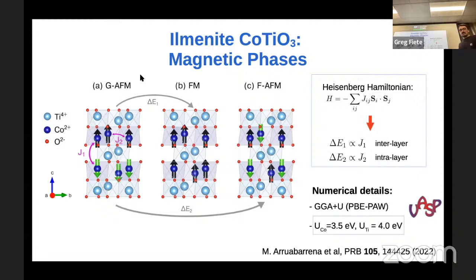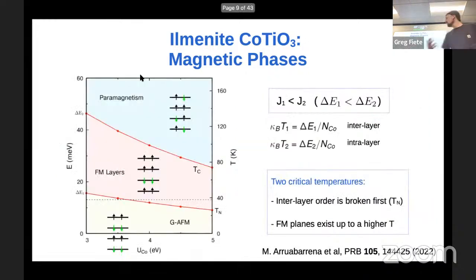What we found when studying the magnetism of this compound via the J1 and J2 constants was the following. We were able to make a phase transition diagram in which we observed that the ground state was effectively the experimentally observed GAFM state, with ferromagnetic cobalt planes that are antiferromagnetically coupled in the z-axis. But then we also observed that the intralayer coupling was larger than the interlayer coupling. What does this mean? That it's easier to break the interlayer magnetic order than the intralayer one. So this means that we will have two critical temperatures.